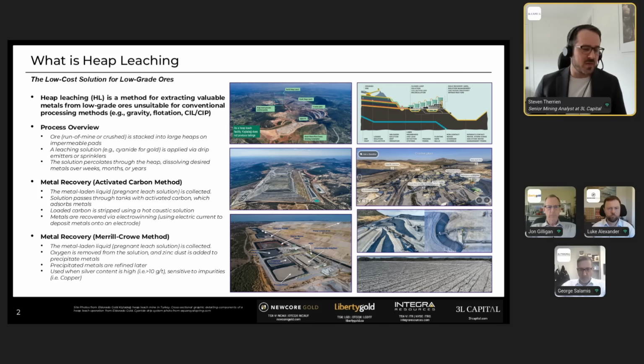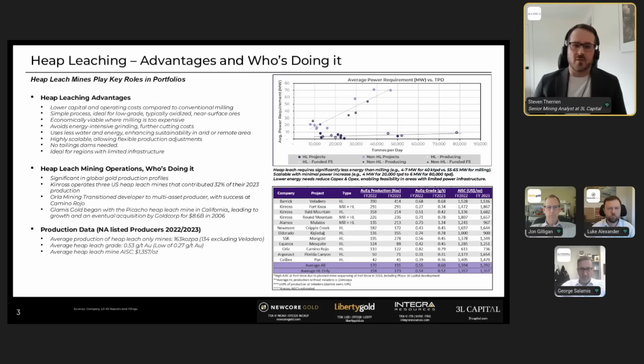And I just got some good pictures from El Dorado's heap leach mine, which you can see in detail and verify on their website. Heap leach is often favored for its lower capital and operating costs, simplicity, and suitability for low-grade, typically oxidized near-surface ores. It uses less water and energy versus milling operations, enhancing sustainability in arid or remote areas, and is highly scalable, allowing for flexible production. While recovery rates are typically lower, 60 to 85% versus 85 to 95% for milling, the trade-off is acceptable for low-grade ores, or in unstable regions due to lowered financial risk from smaller initial investments and easier site closure. They play an important role in producers' production profiles globally.